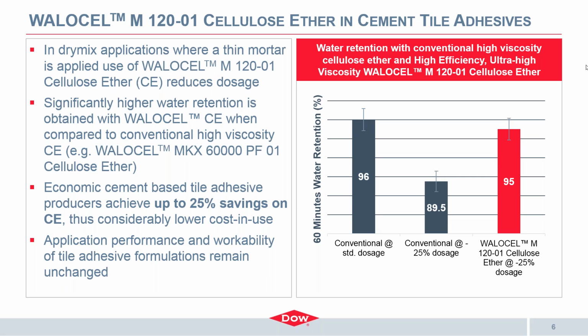And for our new WALOCEL M 120-01, water retention at the reduced dosage is much higher. It's 95%, and that's essentially comparable to the value of the regular cellulose ether, but at 25% dosage reduction. So these results confirm the unprecedented water retention capability of WALOCEL M 120-01 and enable producers of cement-based tile adhesives to save up to 25% dosage of cellulose ether compared to any regular high viscous cellulose ether out there, without compromising workability and having the same application performance.